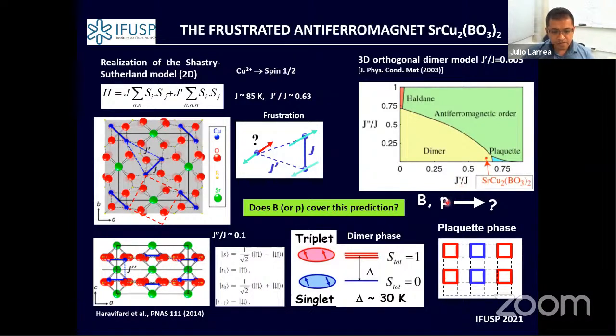By changing this ratio, for instance through application of pressure or magnetic field, you can tune the system from the dimer singlet phase to simply a plaquette phase. In this case, the plaquette phase contains an entanglement of 4 nearest-neighbor dimers. If you continue increasing pressure or magnetic field, you pass to another phase: the quantum antiferromagnetic order.